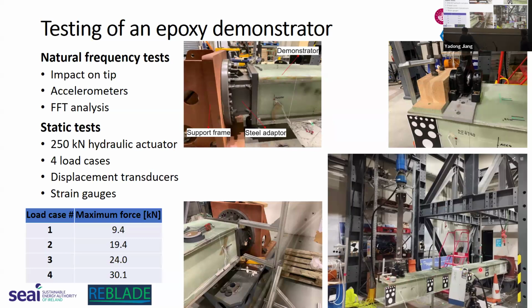The demonstrator is mounted as a cantilever beam, and at the supports you have several very heavy steel components to fix its root, and at the top you have a 250 kilonewton hydraulic actuator to apply the compression load through the extension bar. Along this bar, we have several strain gauges and displacement sensors installed. During the static test, we applied 4 load cases until the failure occurred, and I will go through it later.